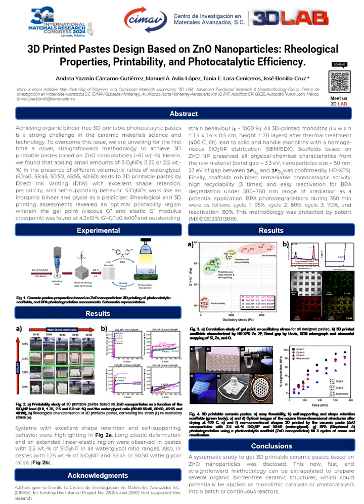And results, as shown in Figure 2: the pastes that obtained the desired properties were those that had 2.5% by weight of silicon oxide in all volumetric ratios, 60-40, 55-45, 50-50, 45-55, 40-60 water to glycol, and those of 1.25% with the ratios 55-45 and 50-50. All this is verified with the rheological properties.